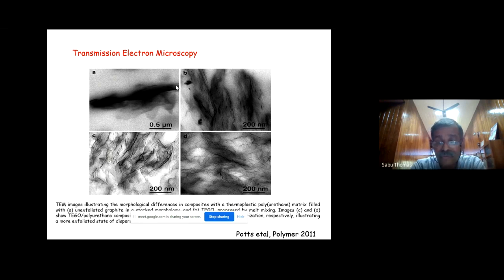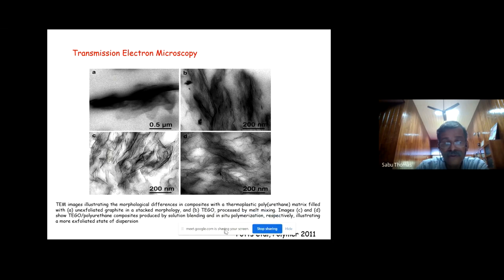nanocomposite. We work on polyurethane a lot, but this is work reported by a good friend of mine, Professor Potts. He worked quite a lot on thermoplastic polyurethane. When you mix thermoplastic polyurethane with graphite, you see it is unexfoliated. Graphite is not exfoliated. In figure B, this is thermally expanded graphene oxide processed by melt mixing. Look at this, relatively good dispersion of graphene oxide. C and D are produced by solution mixing and by in-situ polymerization. So you find that solution mixing and in-situ polymerization gave rise to excellent dispersion of graphene oxide in polyurethane.